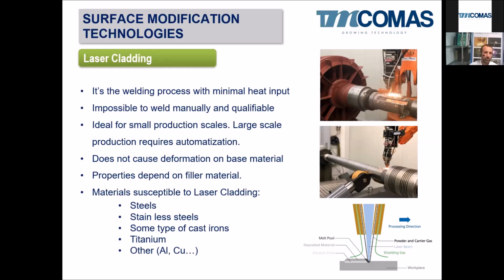Other things: it's not possible to weld manually. As you can see here, the optics are quite big and quite heavy, so it has to be done by a robot or by a CNC machine. So it's an automatic process, which is good for one thing. It's very reliable, one layer after the other. It's qualifiable as a normal laser welding process. So we can have a qualified operator, we can have a WPS. So everything can be qualified to ensure a good quality of our claddings. I would say it's ideal for a small production scale, but also depending on the automatization, you can achieve very high output.